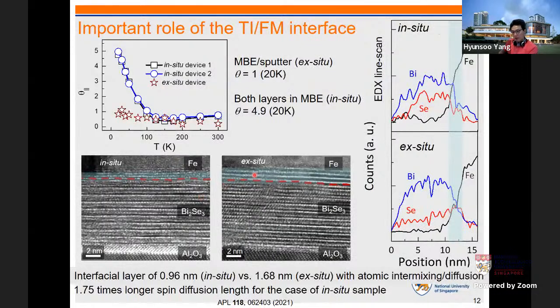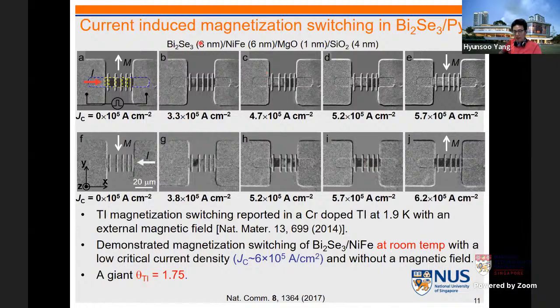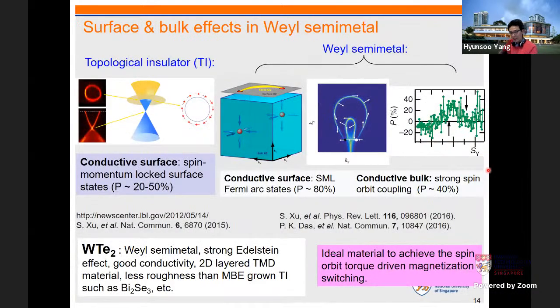Even though we can see room temperature switching and very large spin Hall angle, we still have a serious current shunting issue because bismuth selenide is about 2 orders more resistive than the nickel iron. So when we inject current, lots of current will be shunted through the nickel iron layer without going through bismuth selenide. So those will not be able to generate the spin current. To mitigate this, we try to use another material, Weyl semimetal. As I mentioned, the Dirac cone is now separated. Then the property is metallic, but at the same time, it has a strong bulk spin-orbit coupling. So even though there could be some current shunting through the bulk, we don't need to worry about it. We can still utilize a strong spin-orbit coupling effect. So this could probably improve this current shunting issue in our devices.